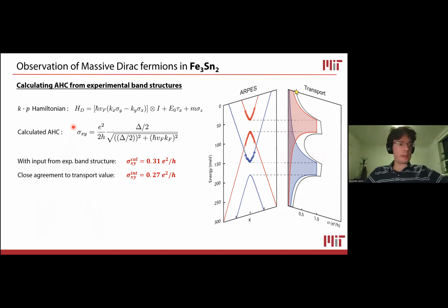But the interesting thing is that if we take this dispersion and we analyze it, and we look at the spin-orbit gap that exists at the K point, which is of order 30 milli-electron volts, which we can obtain from the ARPES dispersions, shown here in the data points. So if you do a k·p modeling of this band structure and you calculate the resulting sigma xy, or the resulting anomalous Hall conductivity, by assuming the Fermi energy is where it is experimentally, then you get a value which is within 10-15% of the value that was observed by transport. So this suggested that there was a strong connection between the electronic band structure and the transport data, which we could validate quantitatively by looking at the dispersion of these massive Dirac fermions in the system.